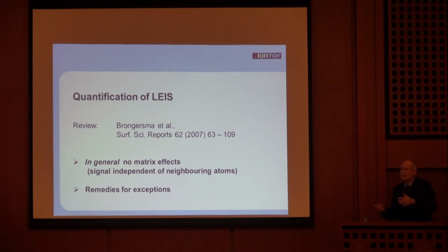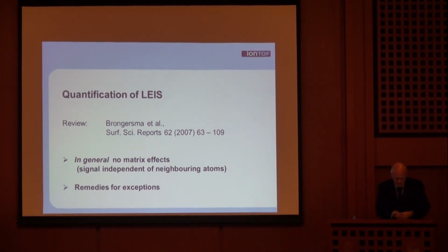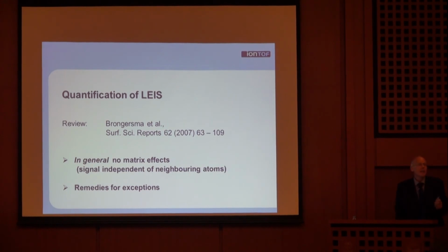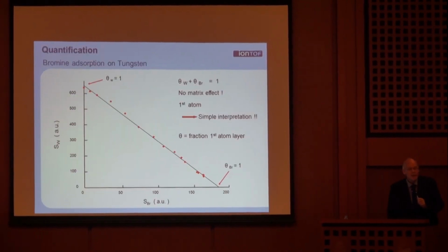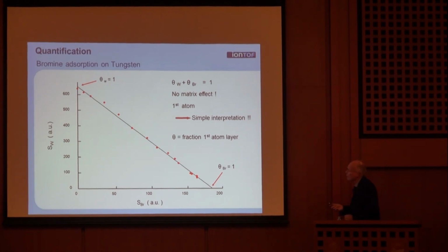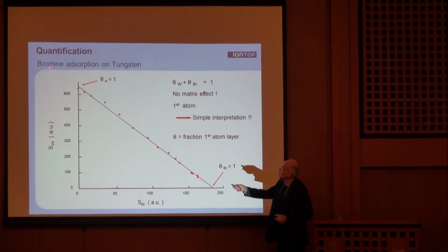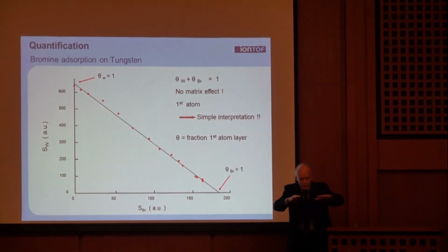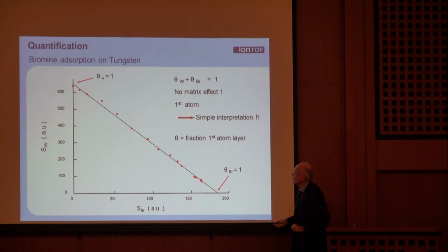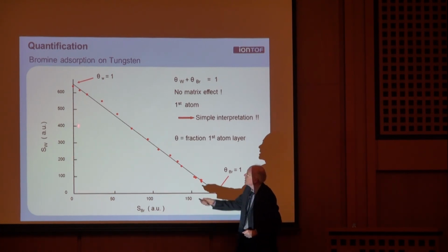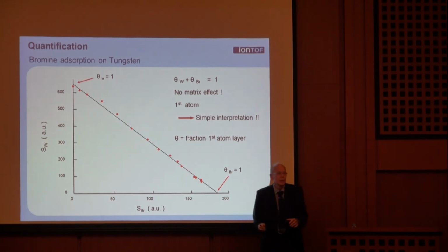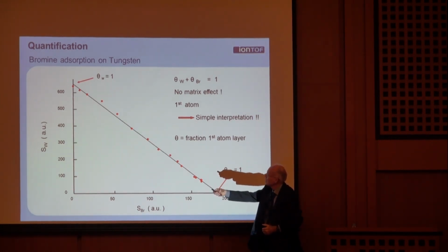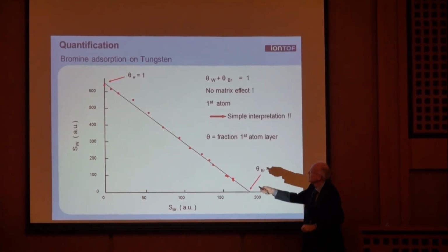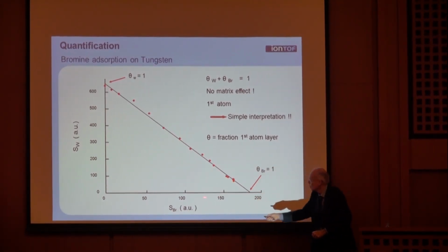Now, quantification is a long story, and for those who are really interested, you can find a publication on it. I'll give you just one example to illustrate how you do quantification. And this is the adsorption of bromine on top of tungsten. So just flat tungsten and I adsorb bromine atoms. In the beginning I do ion scattering and it is pure tungsten. So okay, I get a high tungsten signal. And when I adsorb bromine, the tungsten signal goes down and the bromine signal goes up, linearly.